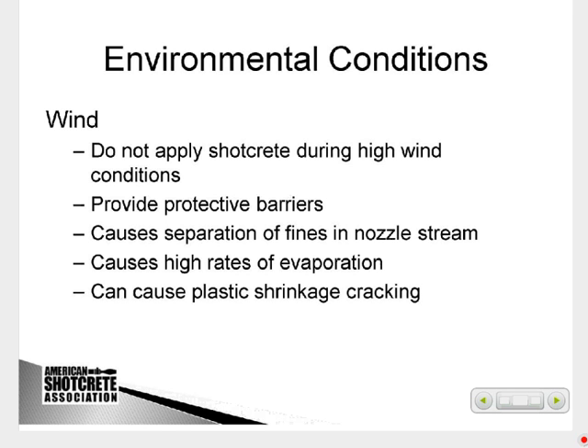Wind, if you have a very windy location where the wind is coming across the surface that you're shooting against, it can tend to separate the nozzle stream. You can get in closer and help prevent that, but when you reach a certain point with high winds, you just can't shoot unless you put up a barrier to basically block the wind. You can also use different nozzles to help concentrate the stream, the material flow, so that you can counteract that wind trying to separate your nozzle stream. But that's really dependent on the job, on the exposure, the amount of wind that you have, whether you're doing wet mix or dry mix. These things all come into play when taking wind into consideration.